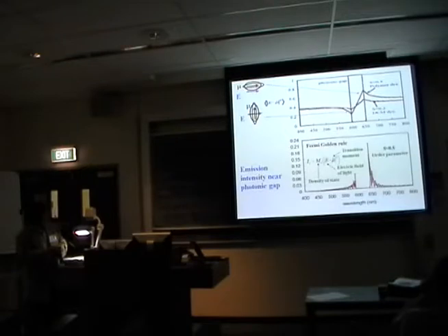Since the order parameter of the polymer dye is larger compared to the commercial dye DCM, at the lower energy edge the dipole and electric field are almost parallel to each other. So this value becomes largest here.